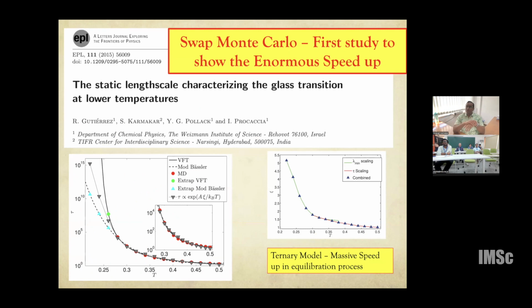Still the rates are around 10 to the minus 3, or around minus 2 to minus 3, but that itself was large enough to accelerate the dynamics very, very significantly. And we could equilibrate the sample at a temperature where the estimated relaxation time can be as large as 10 to the 10 to 12. So this is nearly impossible using any conventional methods.